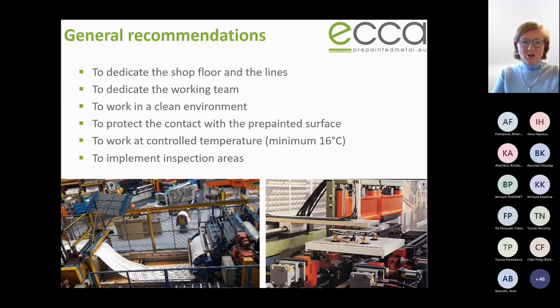About general regulation, it's important to dedicate the shop floor and the line, so the coil coating line, steel service center, and other customers, to dedicate the working team to work in a very clean environment, no dust, to protect the contact with the pre-painted metal, no contact with metallic material, only rubber and Teflon to protect the pre-painted metal, to work in a controlled temperature, be careful, not below 16 degrees because it's too cold and we have the risk to have cracks, and to implement an inspection area. It's really a finished product. We have to supply to our customer without any dust, without any defect.